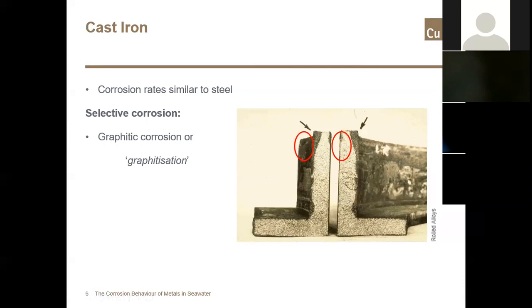At first glance, the surface may appear reasonably normal, just covered in rust, but underneath is a rather flaky, crumbly structure with a serious loss of material. And you can see from the image on screen, the darkened area around the edge of the cross section would be where the issue has occurred, and the lighter material is the more virgin material that was designed to be used. So you can appreciate that carbon steels and cast irons both corrode in aerated seawater, but on the whole they're lower cost alloys.